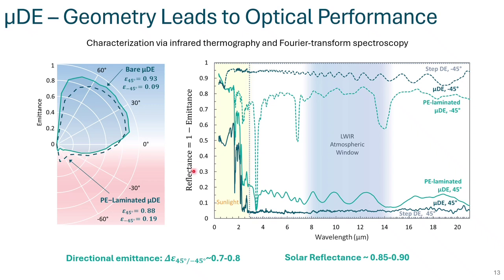On the right, we now show the spectral reflectance of the directional emitter. Since reflectance is essentially 1 minus the emittance, the same conclusions apply. We observe strong reflectance and low emittance below the horizon due to the metallic tilted facet, and low reflectance and high emittance above the horizon due to the intrinsic emittance of the polymer substrate. Lastly, over the solar spectrum, we note a high reflectance thanks to the nanoporous polyethylene laminate mentioned earlier.